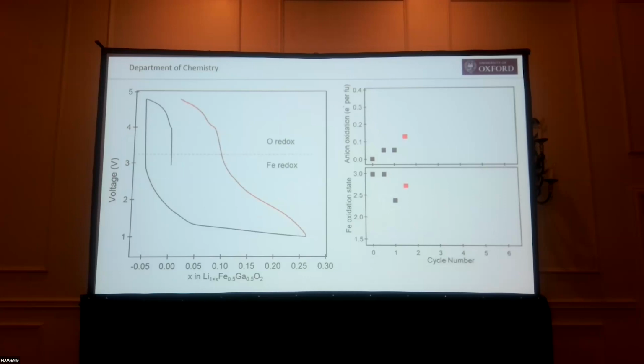Then if we look at the shape of this curve, you can see there's a low potential oxidation and then a high potential oxidation. We make the distinction that this is iron redox, so this is oxidizing iron 2 to 3, and then this is anion redox. We can partition the electrons to give us the iron oxidation state and the anion oxidation. And again, in the reduction, we come back down again, with no indication of oxygen reduction. This is all iron.